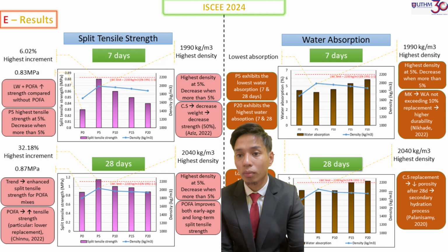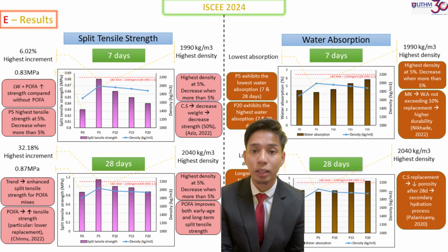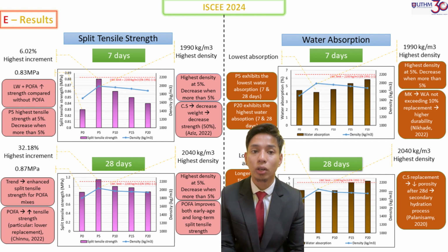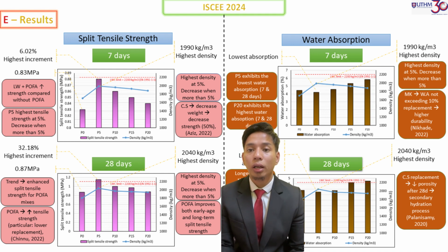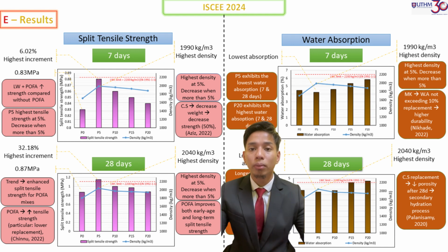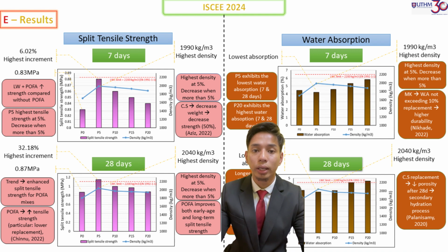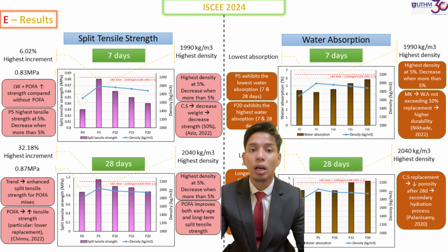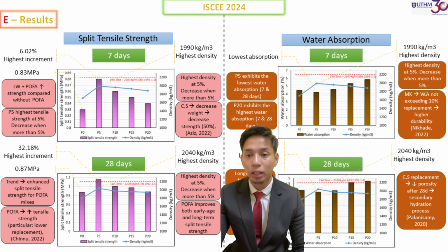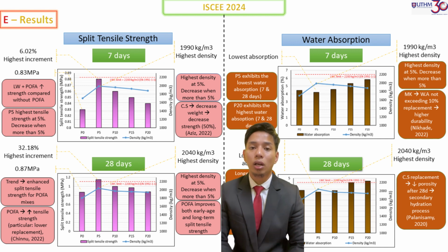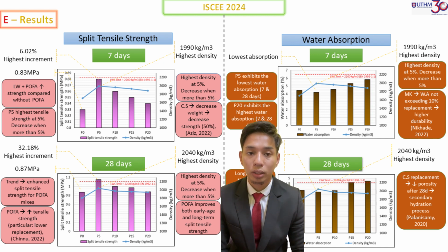Because according to Thomas, who discovered that concrete samples containing 10 to 20% of POFA exhibit higher tensile strength compared to the control specimens over a 90-day period, with a trend similar to the compressive strength of control OPC concrete. MNR also determined that the optimum strength in concrete required the inclusion of Metakaolin and POFA at concentrations ranging from 10% to 15% and 10% to 20% respectively. According to Aziz, adding coconut shell aggregate to regular concrete decreases the compressive strength, splitting tensile strength, and